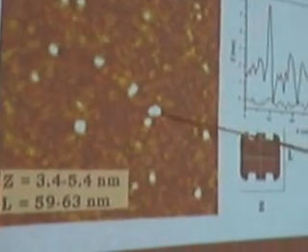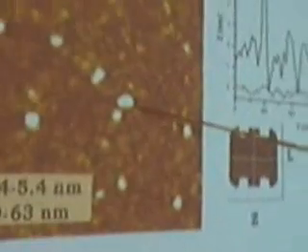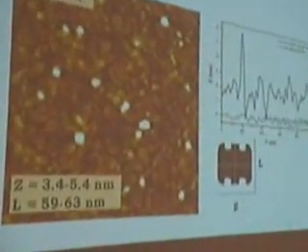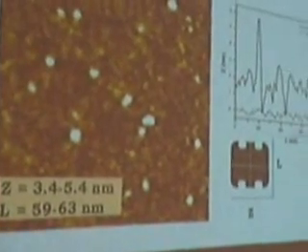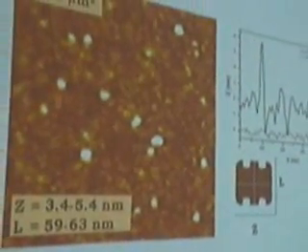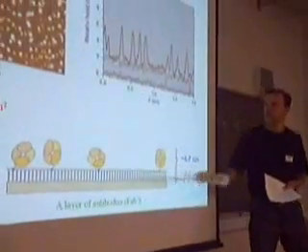So indeed, well, this is a little bit too large, the lateral dimensions, but the height information is very reliably obtained by this technique. So we can read out where our proteins are on the surface, we can read out their dimensions, especially height, and we can even calculate the yield of adsorption. And we can make the same kind of analysis for Fab fragments, for example, that have been immobilized there. Now we clearly have a high concentration of immobilized molecules. And since we have quite homogeneously distributed these linker lipids, we have a quite even distribution of these Fabs at the surface.